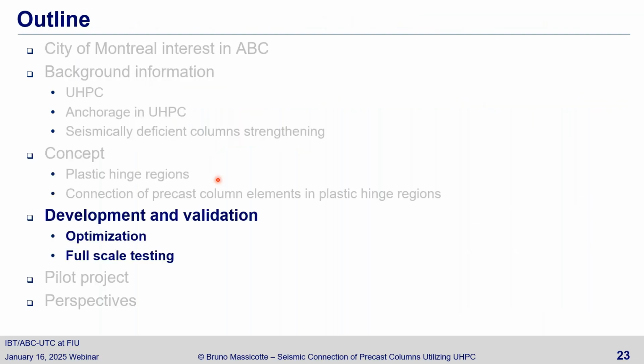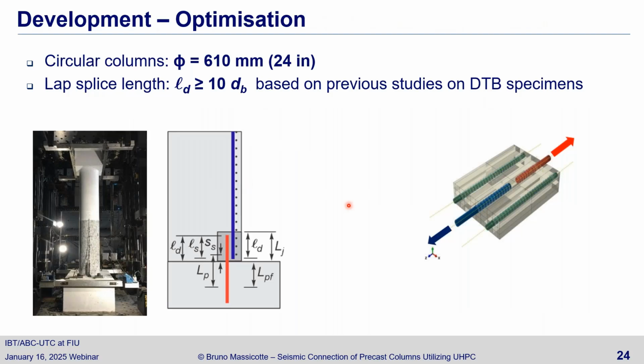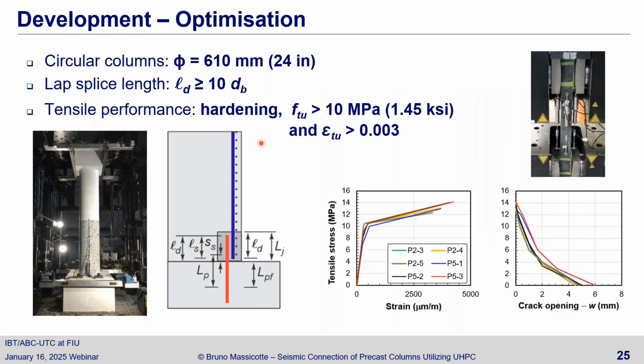So as I said initially, this solution was not optimized for the strengthening of columns. The first specimen I tested was a circular column 2 feet in diameter, and we started with a lap length of 10 bar diameters to be just below. I was hoping to be a bit below the target value, so that I could see how much improvement I needed. We picked the UHPC that had that property, and this is a very commercially available UHPC in North America, so nothing fancy.